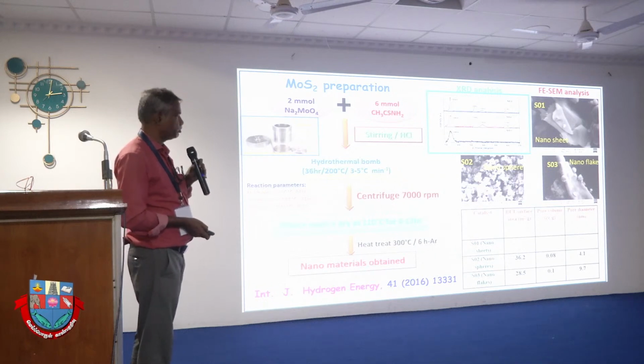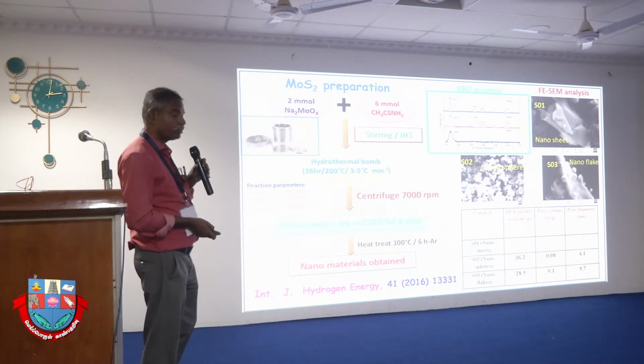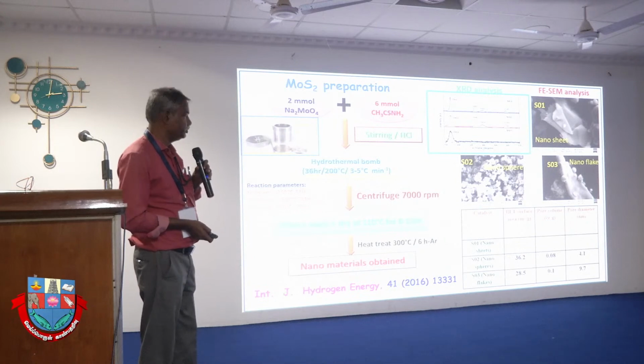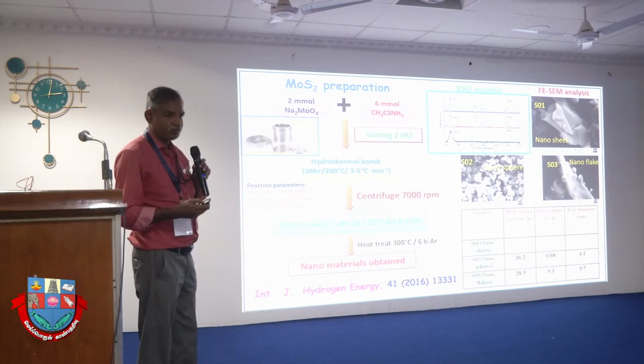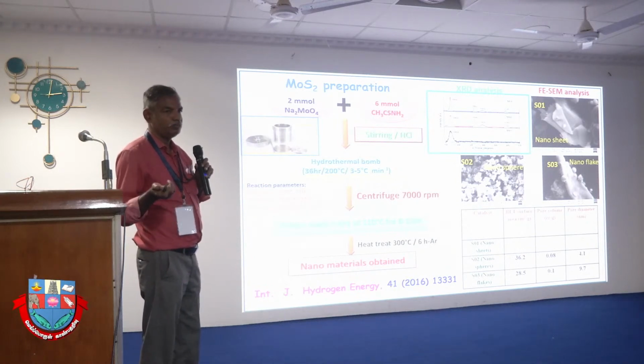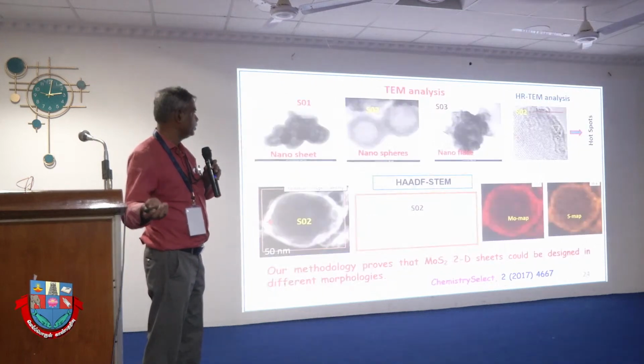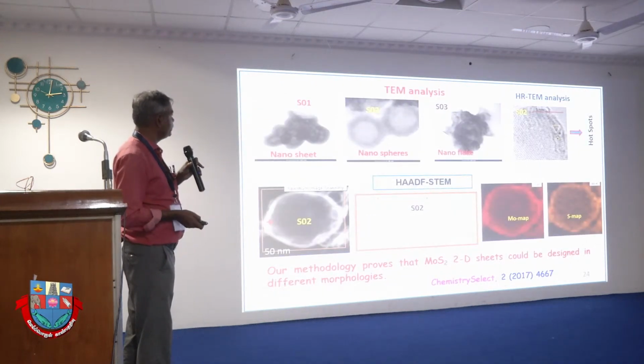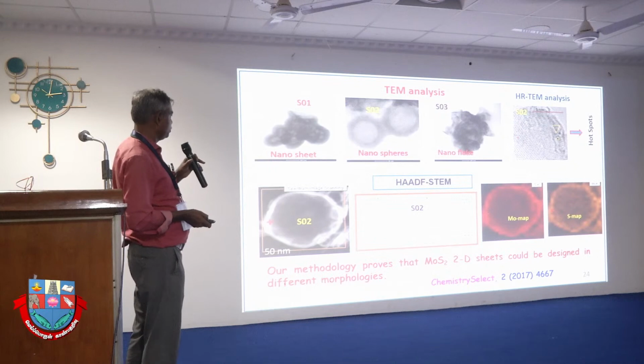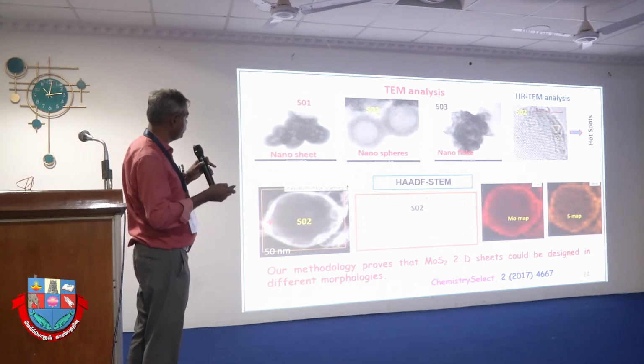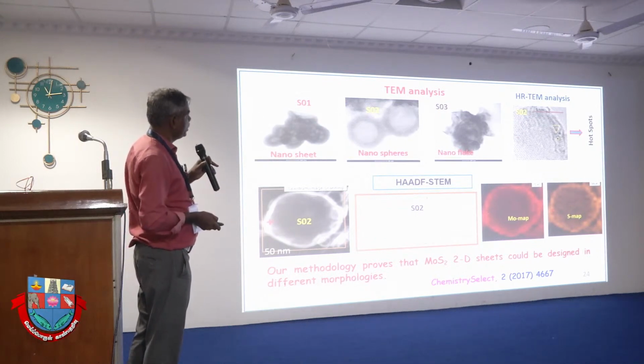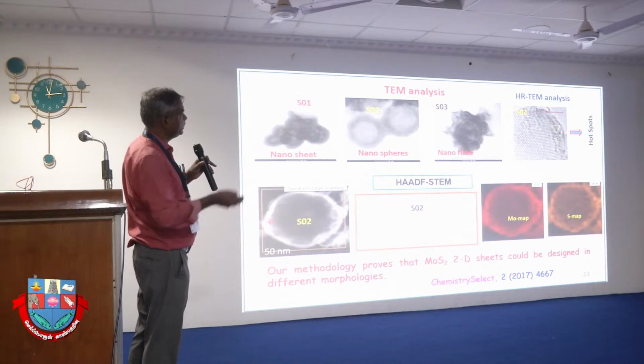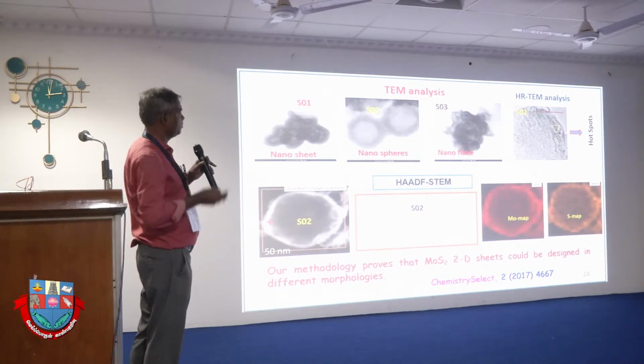forms 36 meters squared per gram surface area, and the nanoflakes form 28.5 meters squared per gram. So you have a difference in surface area if you change the morphology, because of morphological factors. And then if you go for TEM analysis, you can see that the shape of the materials is totally different, especially the nanospheres have some defect sites on the outer surface of the sphere.